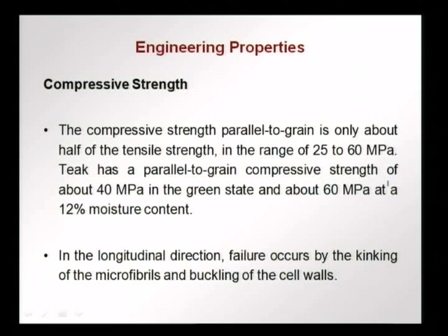So, that is what we say here. In the longitudinal direction, the failure occurs by kinking of the microfibrils and buckling of the cell walls. If you can imagine these fibers like a bunch of straws, and if there is load in the direction of the straws, the straw walls buckle.